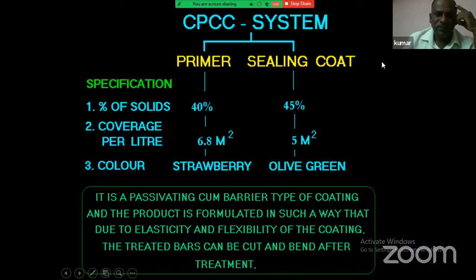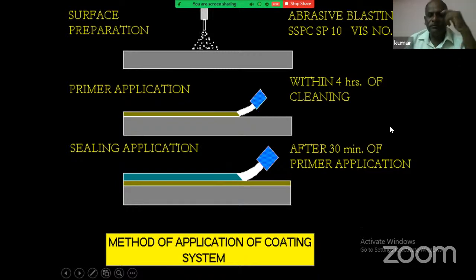Now this is the system. It has a primer and a sealing coat. The primer polymer content is 40%. The color is strawberry. The sealing coat has 45% polymer content, solid content, and olive green color. It is a passivating cum barrier type. It has both the advantages. This is the application procedure. The surface is to be properly cleaned, either by abrasive blasting or any other means, without any corrosion product. Then the primer is to be applied by dipping, brush or spray. After that, the sealing coat is to be applied. That's all, the process is over. Allow for curing.